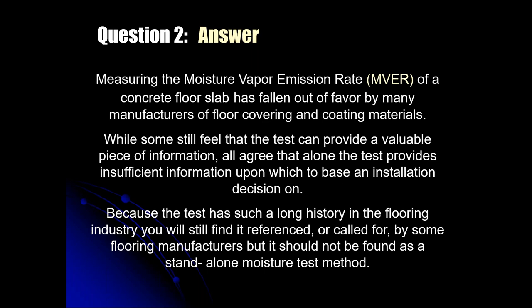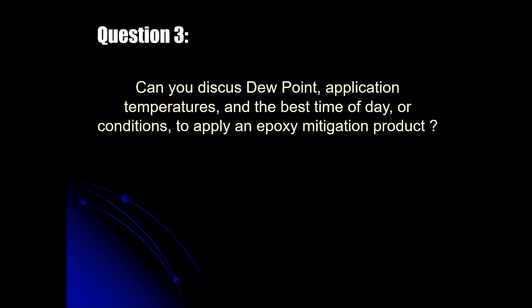But without hesitation, I will say that if measurement of the moisture vapor emission rate by the calcium chloride method is the only test you conduct, you have insufficient information to base a flooring installation upon. I am in the group that still believes, I like to have every piece of information I can have. So I still conduct the test to obtain a piece of information. But again, alone, it's totally insufficient information.